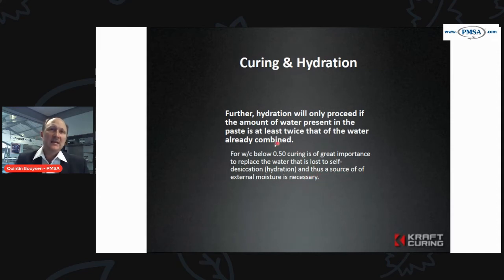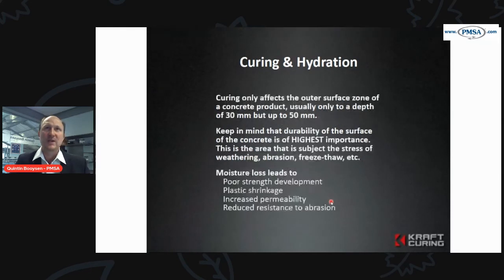So part of that 0.5 water that we have in there, the water cement ratio, part of the water actually gets used up in the hydration process. And we need to replace that with an external source. And that's where a curing system is critical, because it actually replaces where that water is being lost, and it re-adds the moisture back into it to allow the hydration to continue.